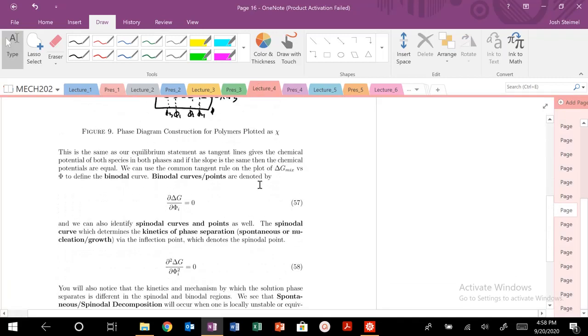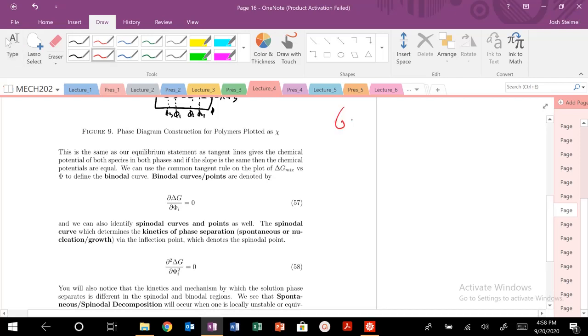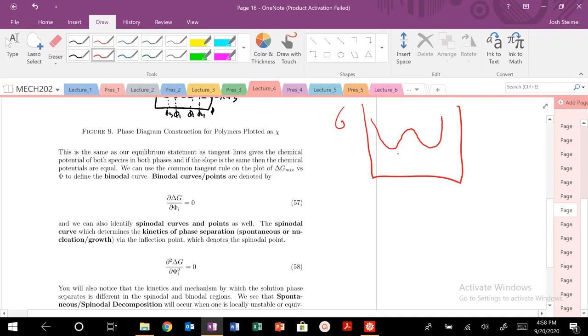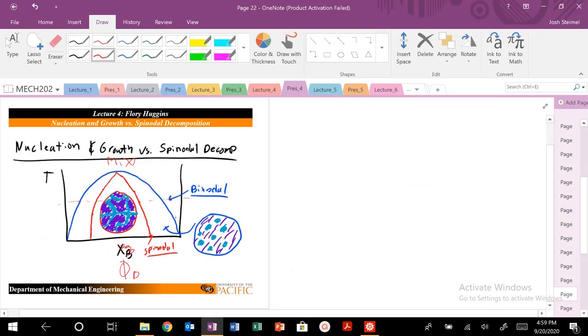Let's look at how we can define that mathematically. We can draw the full phase diagram by finding the points where we have a common tangent. Looking at the general curve — when we have some phase separation — I can find these points in φC by finding that common tangent. This will give us our binodal. Binodal curves give us the points of coexistence.